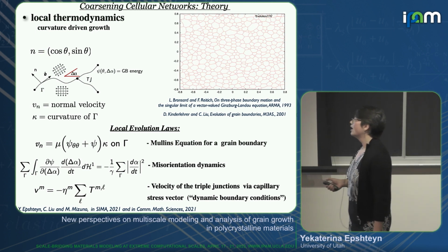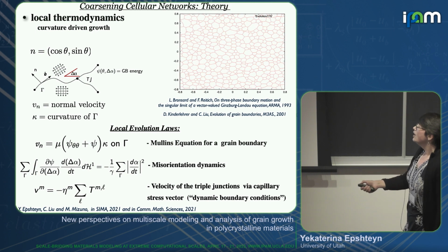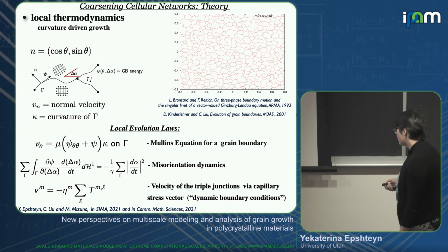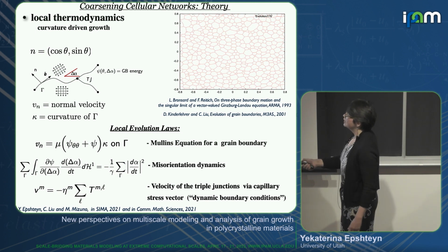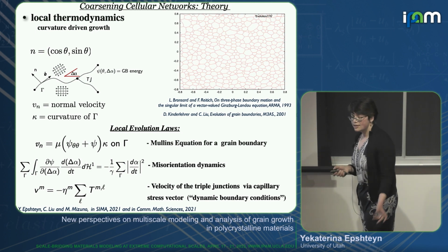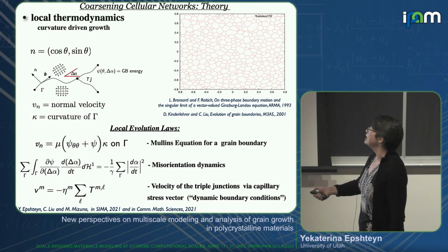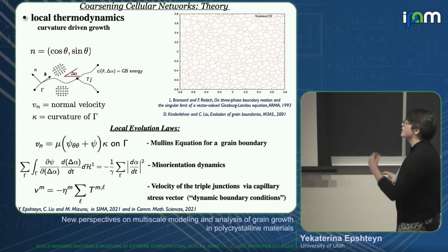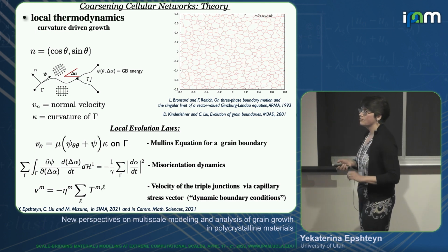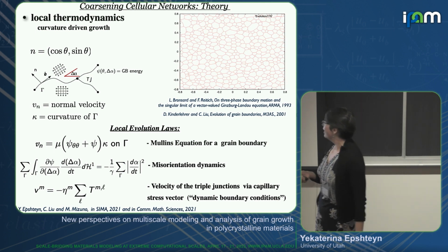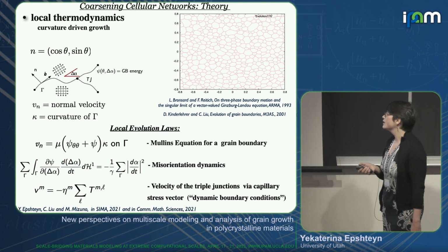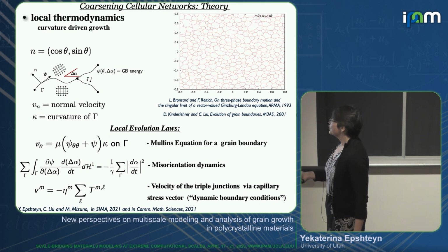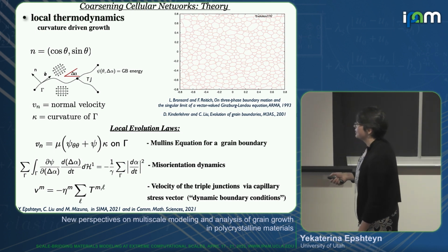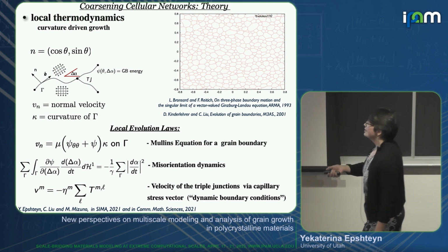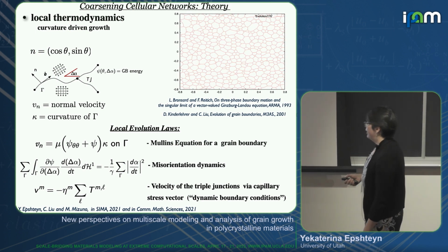Basically, it's a nonlinear parabolic equation, and it tells you that velocity of the grain boundary is proportional to the curvature. Mu here is a relaxation time scale, mobility of grain boundaries. So it's a relaxation time scale associated with dynamics of grain boundaries themselves. And if we don't have dependence on the normal angle of grain boundary energy density, then it simplifies even further. So we have normal velocity is equal to mu psi kappa.